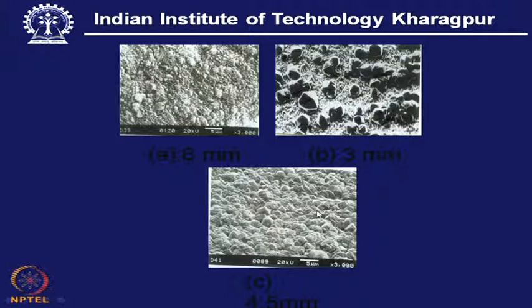But what does this SEM give us? If we see this one, naturally we find a difference. So, that is the reading from SEM. This image and this image, there is a difference. Here we see a well developed crystal with a well defined crystal habit, which is expected from this coating activity. It is a low pressure synthesis. We do not have any high pressure to facilitate diamond formation.